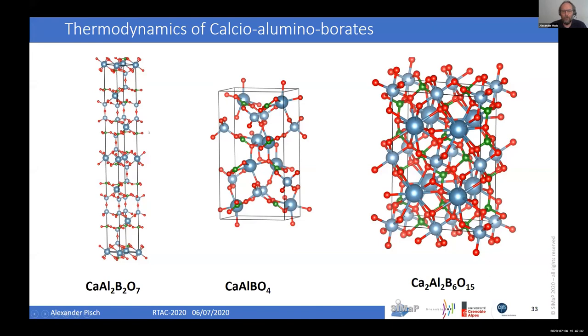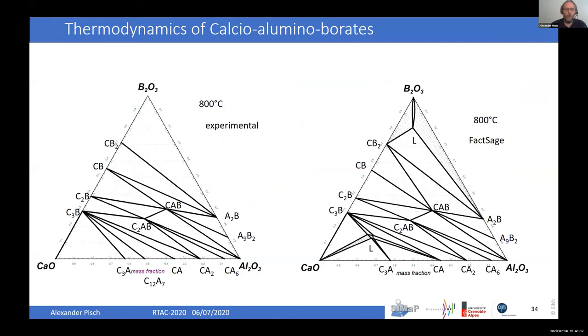So from a structural point of view, they are also different. The two on the left, the aluminium coordination is AlO4. So they have four coordinated aluminium in the structure. On the right side, the aluminium is 6 coordinated. And therefore, the authors in the literature who investigated said it must maybe be a pressure stabilized compound, so only available at high pressure due to this peculiar coordination of aluminium atoms of all 6. So we started the experimental work.